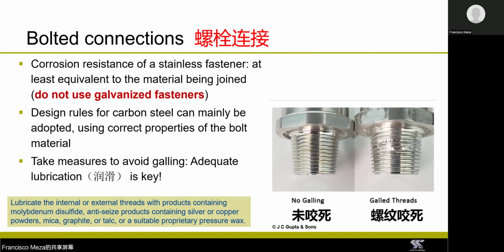So one of the main things that need to be taken into account when designing stainless steel bolted connections is that the bolt, the nut, and the washer should have better corrosion resistance than the connected plates. And this means that you should use stainless steel bolts when connecting stainless steel members. And you should not use galvanized bolts, even in temporary structures, because of the risk of bimetallic corrosion.